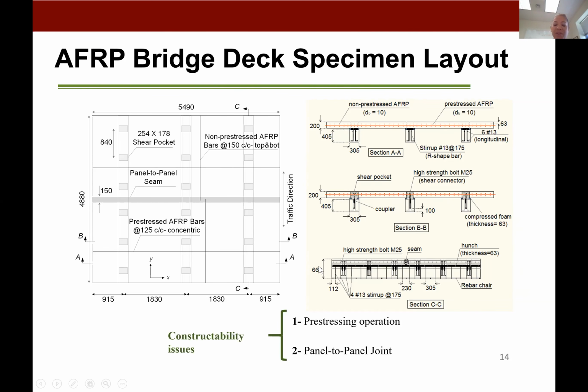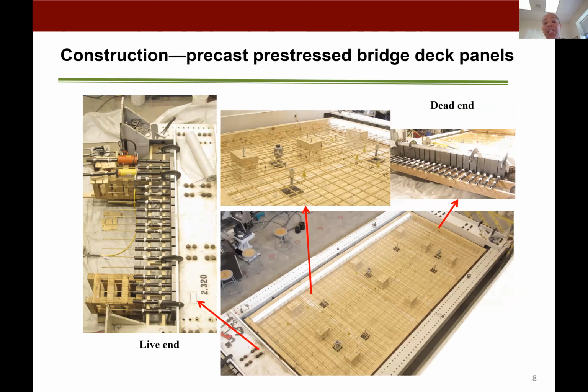So one of the challenges that we saw, and we noted even from the previous examples, in terms of constructability, was what the pre-stressing operation would be, and also making sure that between the panels, we had enough continuous transfer. So we constructed the bridge deck panels side by side with the AFRP bars shown in yellow. In terms of pre-stressing, we had a dead end and a live end with a strong back on the dead end, and we were pulling with a single hole jack per strand. So basically we would pull on the bar with a hydraulic ram. Then we cast a high strength grout into this pipe that actually took about 3 hours to get a full set. So there was a lot of time and a continuous operation there.